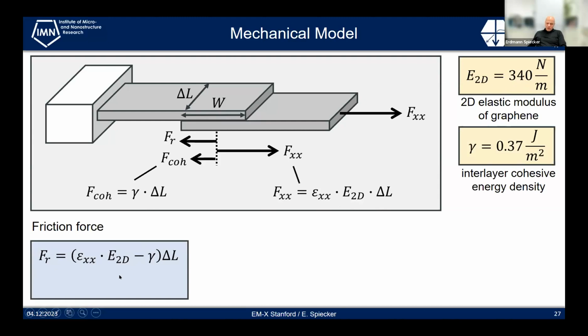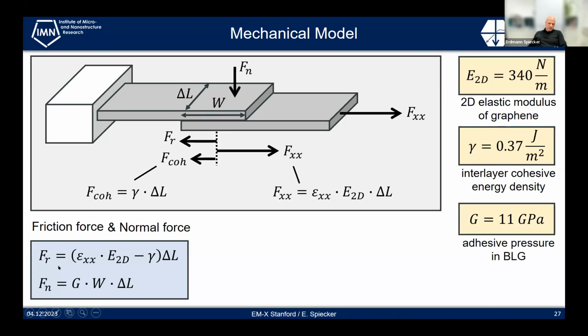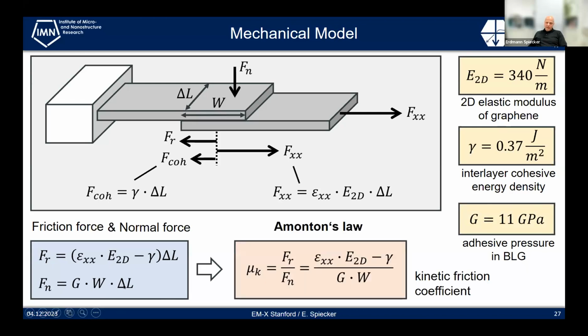And in order to determine a friction coefficient, we also need the normal force, because the friction coefficient, as we will see in a second, depends on both the friction force and the normal force. And for the normal force, we can use the adhesive pressure in bilayer graphene, which is shown here, and of course the area, which is W times delta L. So using Amonton's law, which says that kinetic friction coefficient, or also the static friction coefficient, is the ratio between the friction force and the normal force, we can now insert these formula here and get an expression for the kinetic friction coefficient.